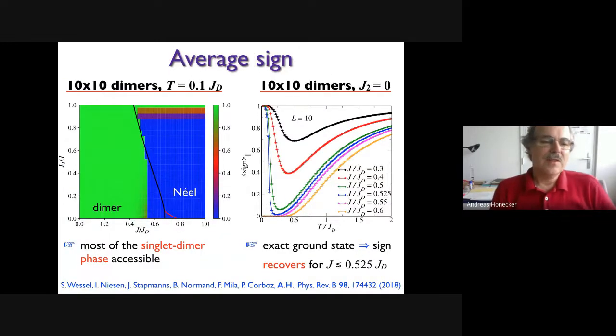Okay, and here's a graph of the average sign. This is 10 by 10 dimers on the left, which is 100 spins, at a rather low temperature. And you see that the sign stays quite close to 1, green means close to 1. It's not exponentially small, it's close to 1 in most of the dimer phase. The vertical axis is the additional coupling J2. The horizontal axis is the coupling between dimers over the dimer coupling. The sign does get small once you go into the Néel phase, but that was kind of the idea.